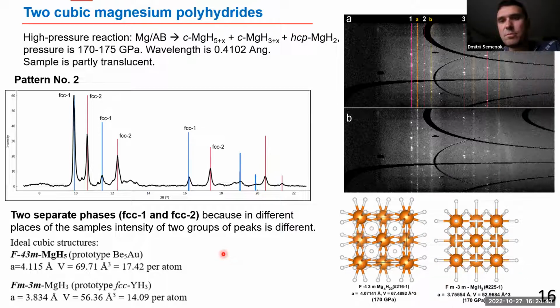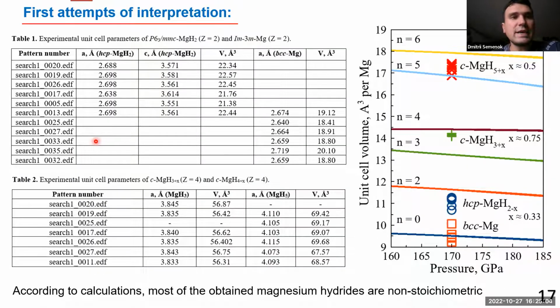the first idea. The problem is that both of those compounds are atomic, should be high temperature superconductors, and they have a unit cell volume much smaller than the experimental volume we extracted from diffraction data. You can see on the left side of this slide the numerical data, maybe for other people who want to try it and confirm our results. I collected unit cell parameters for those cubic sublattices and their volumes for magnesium H5, magnesium H3, and for hexagonal magnesium H2, and for BCC magnesium, and placed it on this diagram with predicted equations of state for various magnesium polyhydrides. You can see that there is a significant discrepancy between the experimental data and theoretical data.